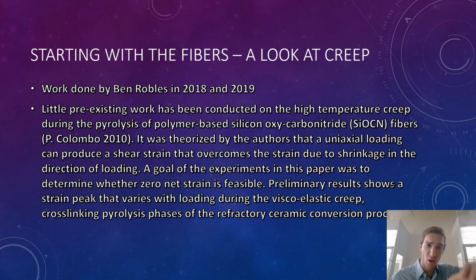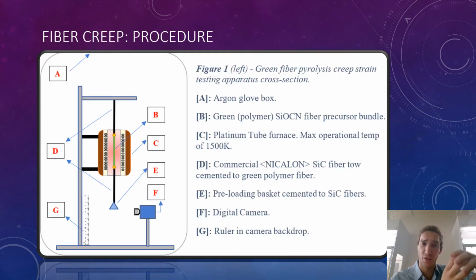So as they're hung, you can see in this schematic here, you run it through a vertical furnace, and then you bring that furnace up from 25 degrees C up through 1,000 degrees Celsius at a rate of 15 C per minute. This allows you to look at the strain and elongation and contraction characteristics of the green fibers as they're under different weights. As you can see in part E, this is the loading basket, so the fibers are preloaded, and then as it's heated up, they experience viscous flow, and then as it undergoes pyrolysis, it shrinks down that nominal 30% shrinkage due to pyrolysis as a reduction into ceramic.